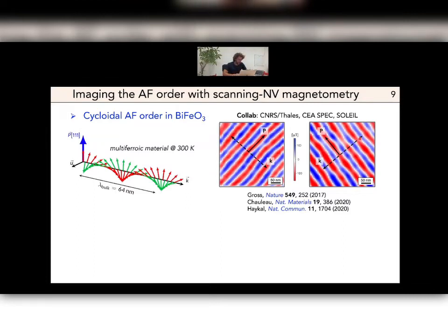This kind of experiment has been done in other types of antiferromagnetic material, for example in chromium oxide by the group of Patrick Maletinsky in Basel, and the one of Christian Degen at ETH. And in this work here, I have shown that they can image domain walls in this magnetoelectric antiferromagnet.